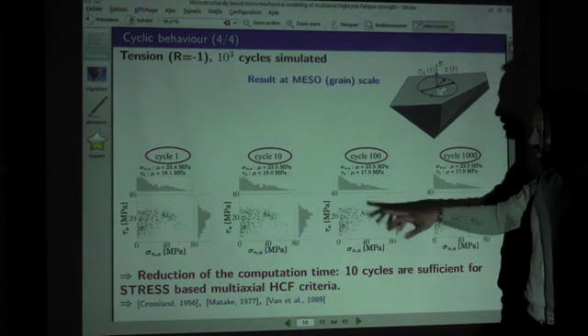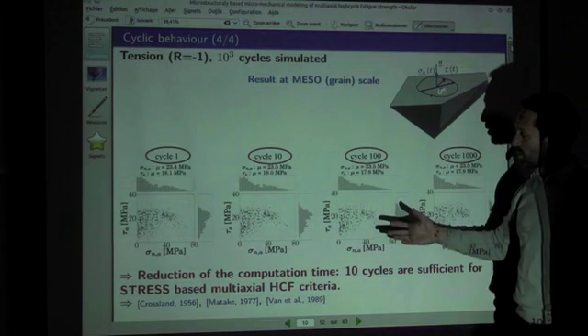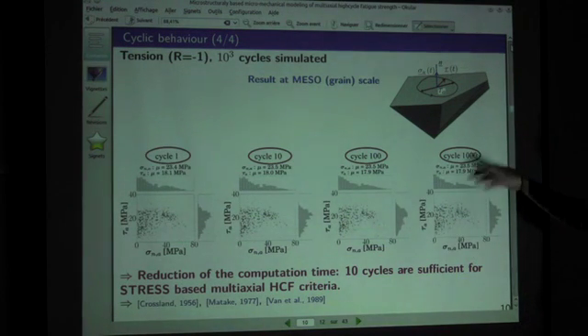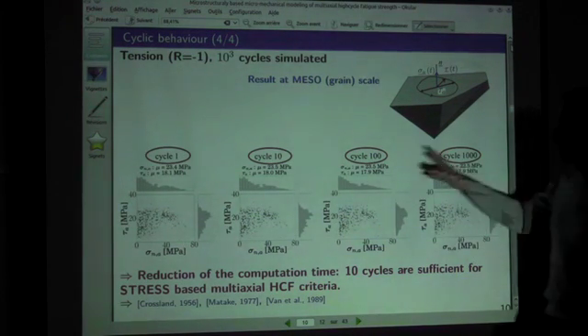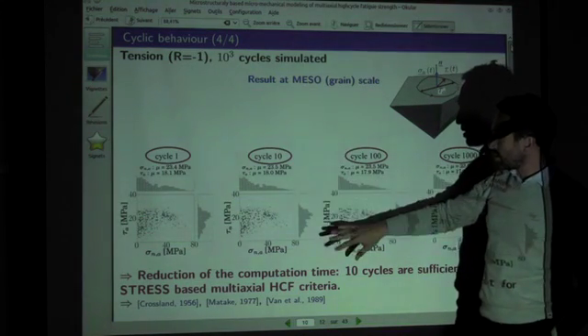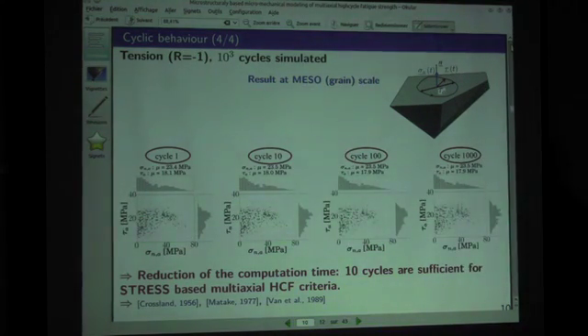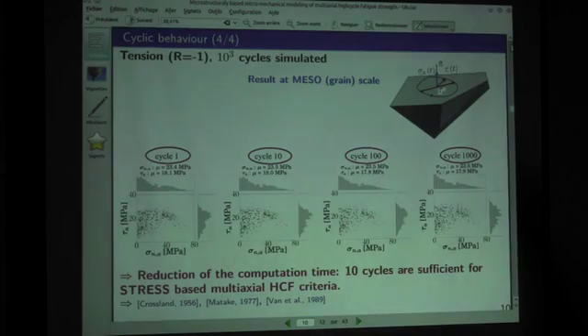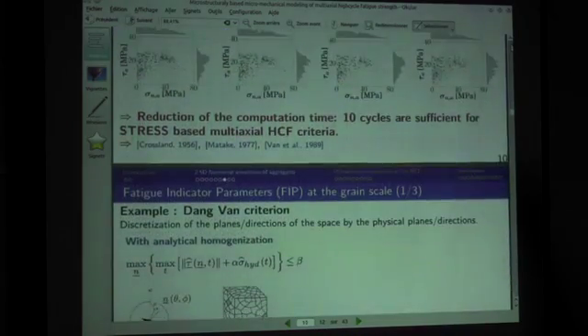So here for our computation, it's a more precise picture here. If you look at the distribution of the shear and normal stresses in the aggregate as a function of the number of cycles, you see that when you use 10 cycles, it's quite enough to get a good picture, or a sufficient picture of what is the local stresses. You don't need to go to 1,000 cycles. That's quite good for us, because otherwise we would have been in trouble. If you do 3D computation, you will see the number of loading cases and computation you have to do. After then, we will have some problems analyzing precisely the data.